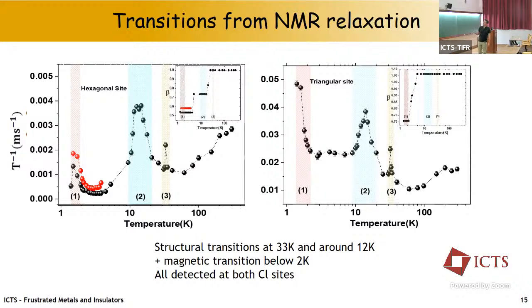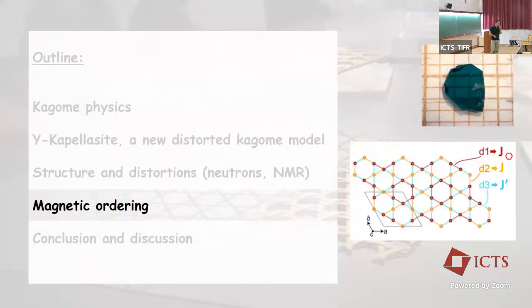So this is summarized here, this NMR study, that's the relaxation measurement. On both sites, we do see a clear, very narrow peak at the first structural transition, 33 Kelvin, then a broad peak of relaxation at this second transition around 15 Kelvin, 13 Kelvin, let's say. And then at low temperature, I'm going to discuss that now, we have a magnetic transition there. Okay. So let's go into the magnetic order.